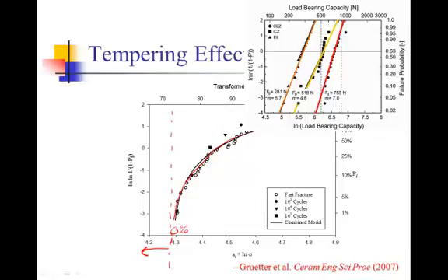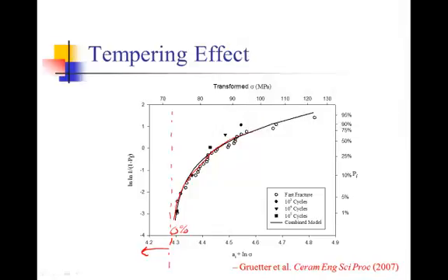below that point. So this has the effect of making the lifetime of the ceramic component less variable. So not only does it make the component stronger, but it makes it more predictable at the same time. And it also makes it less susceptible to future damage, as long as that damage does not penetrate the exterior compressive layer and make its way into the interior region that had the tensile stress in it.